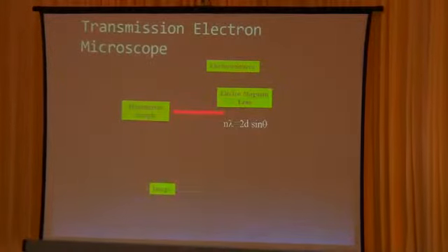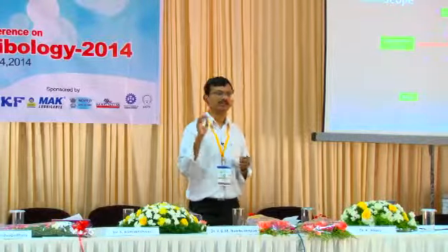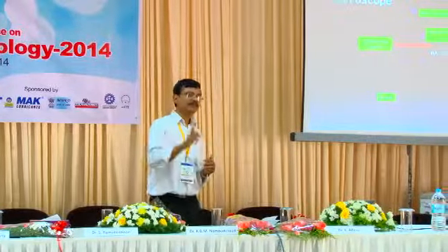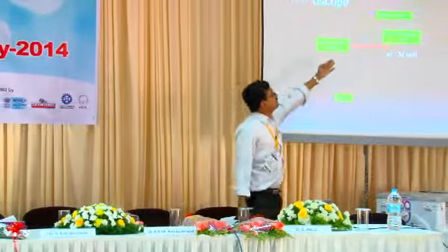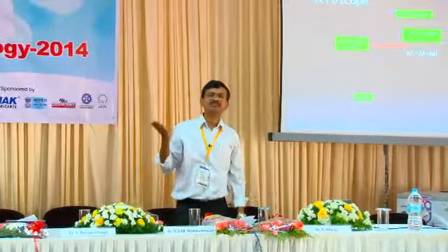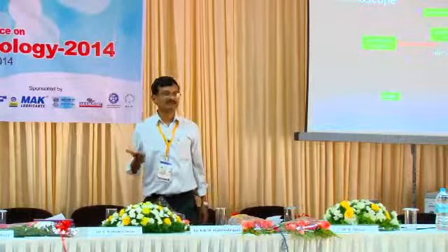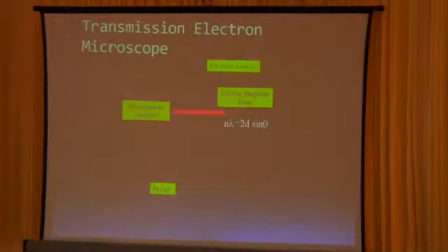So what is a transmission electron microscope? Quickly, a transmission electron microscope is just like an optical microscope. The only thing is the source of image formation is electrons here, not light. We use the wave property of the electrons to form images. So electrons from a source are converged using electromagnetic lenses onto a sample. The sample has to be electron transparent, that is, extremely thin. Extremely thin is 300 nanometers for copper. For aluminum it is 800 nanometers, depending on atomic number. So you have to make it 300 nanometers thin.